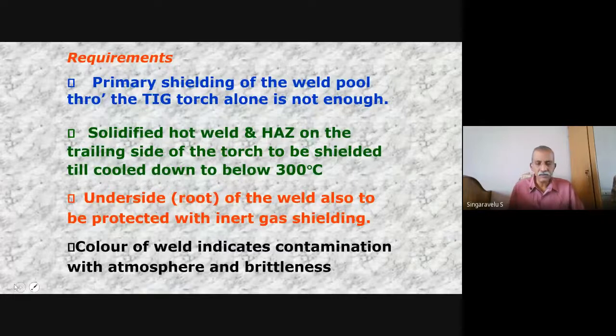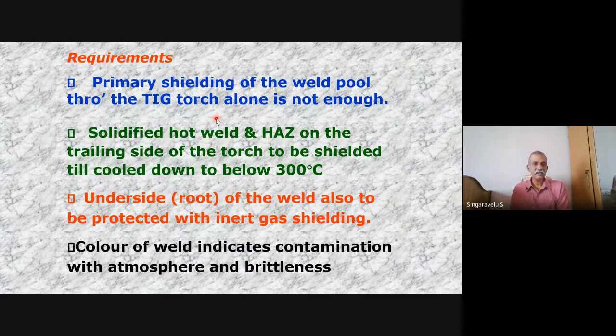So we'll discuss how we can do it with TIG welding, right? Primary shielding, I said, there are two shieldings. One is called primary shielding, another one is called secondary shielding. Primary shielding through the TIG torch alone is not enough. You have to go for additional shielding, we call it secondary shielding. The solidified hot metal, the weld and the HAZ, not only the weld, the HAZ, has to be shielded by the trailing side of the torch. That is, the weld which has been already completed has to be protected from the atmosphere till it is cooled down to 300 degrees centigrade. So we need the shielding. That's called secondary shielding. Root side also, we have to do the shielding by inert gas. These types of shielding are mandatory in TIG welding.